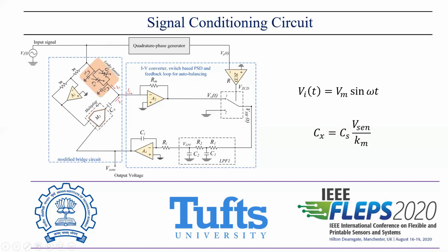So this was done by converting the current in the sensor and reference branch into an equivalent voltage, and then phase shift. Then this voltage was modulated to a higher frequency using a quadrature phase shifter and a phase sensitive switch based technique. So this switch will modulate the information from the sensor into the DC, and the leakage resistance will get shifted into a high frequency. This high frequency component was then removed using a low pass filter, and the integrator in the loop will continuously integrate the value of this low pass filter output till we get a current equal to the sensor information.